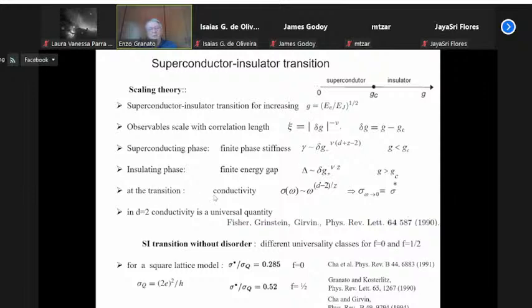Now, right at the transition, the conductivity can be related to the phase stiffness divided by frequency. And from the scaling theory, you can show that the frequency-dependent conductivity scales with a power of the frequency. The exponent is the dimension of the system minus 2, divided by the dynamic exponent. In two dimensions, which is the case we are considering here, d is equal to 2, so the exponent is equal to 0, so this is a constant. That means that the conductivity is a universal value, with no dimensions. And so it is an intrinsic quantity for a particular phase transition that doesn't depend on the details of the model.